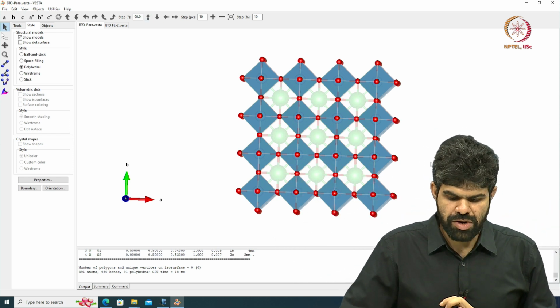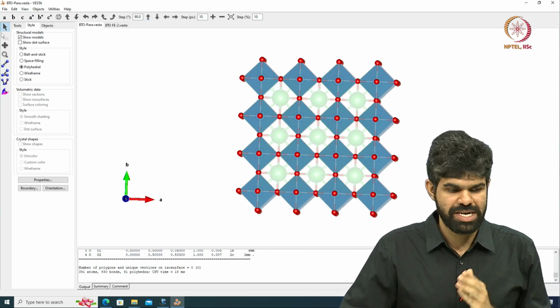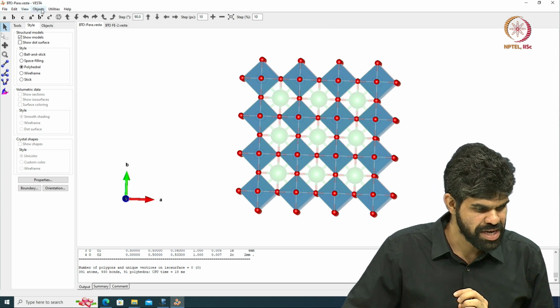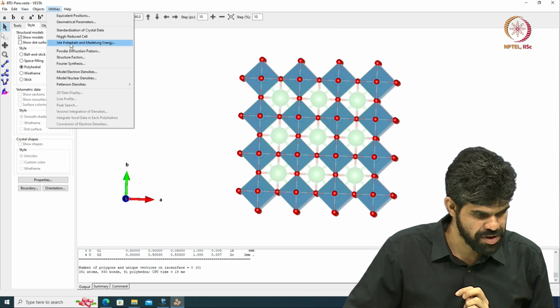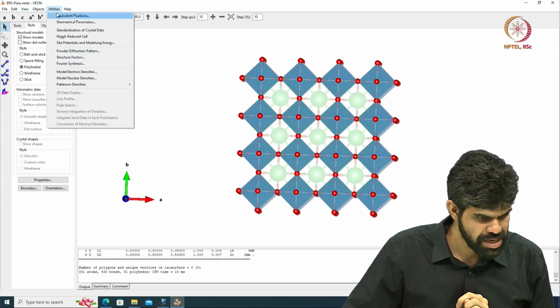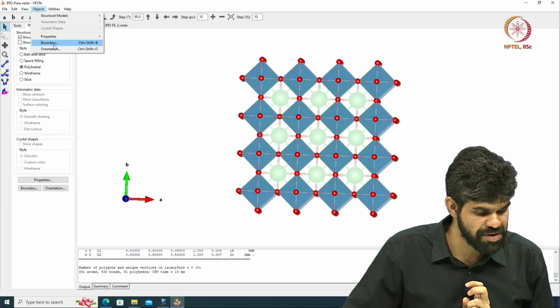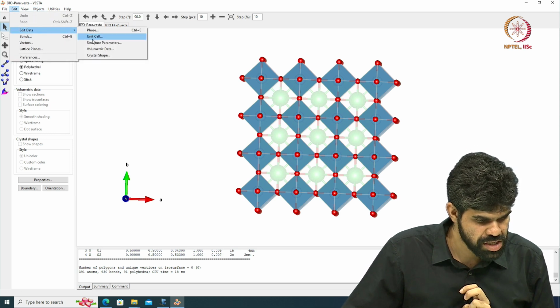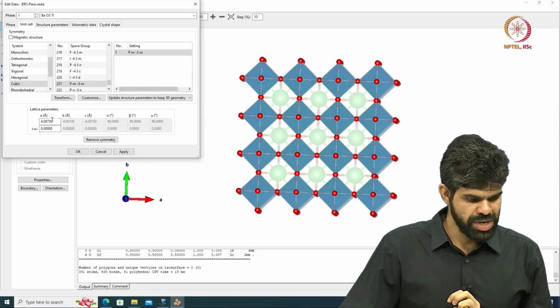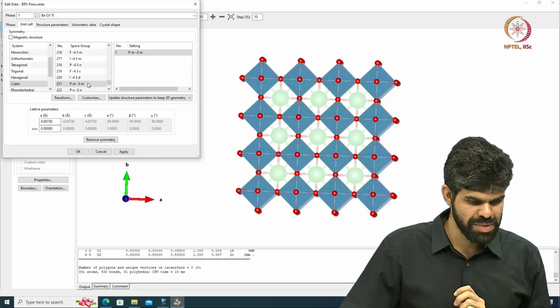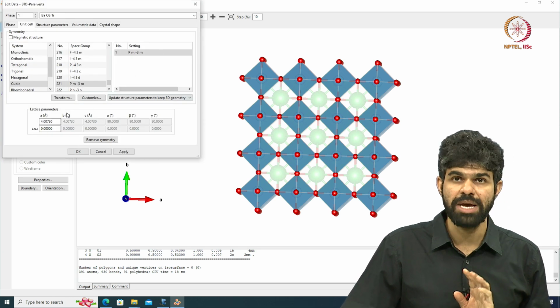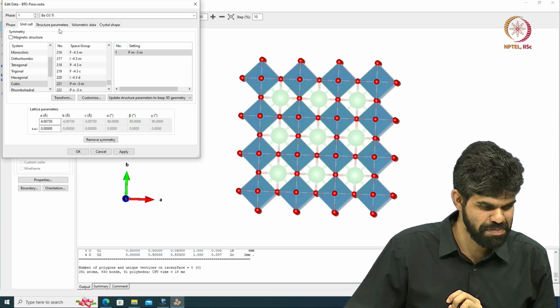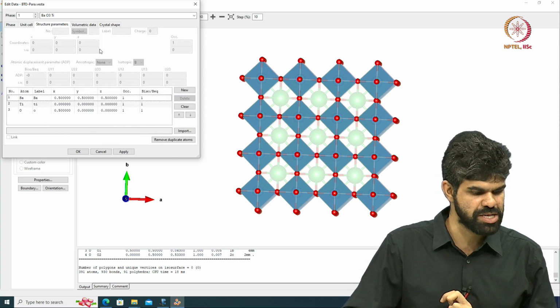Okay. So, this is a cubic barium titanate, and in fact I can look at the positions of where titanium is. These positions can be determined from X-ray diffraction. Let me go to the structural unit cell. So, the unit cell is a cubic unit cell. Pm3̄m, that m3̄m is my underlying point group, the P part we are yet to look at, that is the space group.